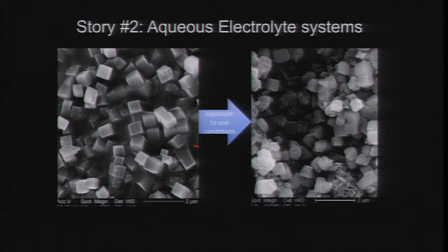And then I see that if I expose it to the wrong environment, and this is an extreme voltage, extreme pH environment, it collapses. We lose the structure. So if I expose it to the wrong use conditions, it will collapse and lose its ability to store energy the way I want it to. It should always look like this. Now, the good thing about water is that there's no SEI formation, so I can get away from that. The bad thing about water is that it often corrodes, especially at negative potentials, any kind of system that I might want to use.